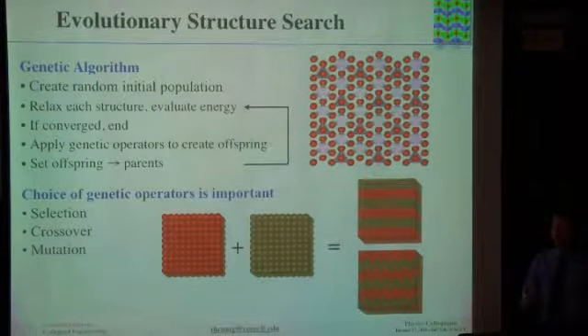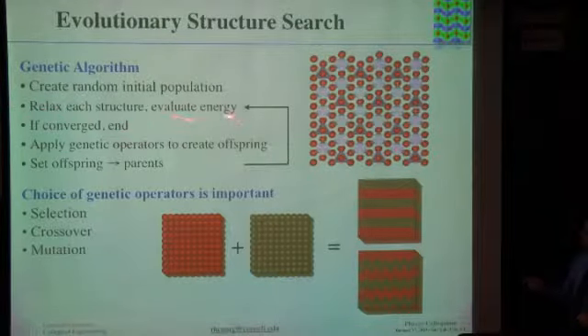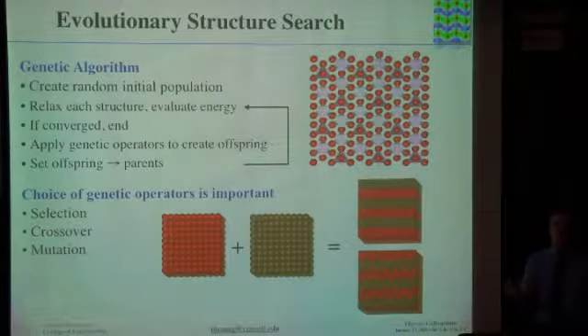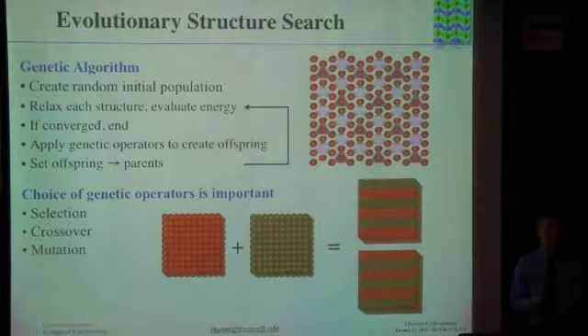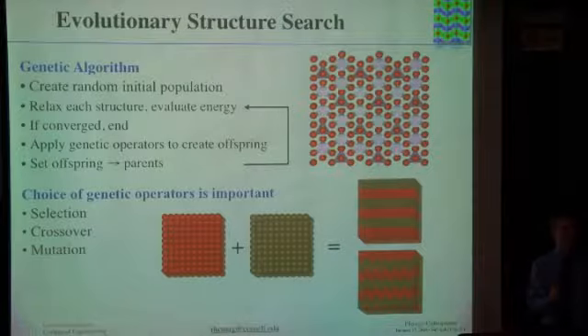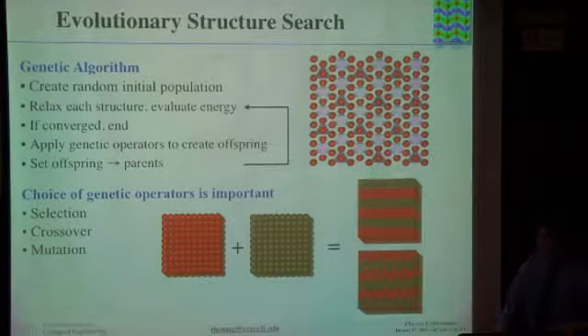We use density functional theory to now relax those structures, to take the forces and stress tensors and minimize the energy, so walk down into the nearest local minimum. That's called relaxation. We look at the energy, and you could stop there in principle. It turns out that if you do 50 to 100 random structures at a given composition, there's a good chance you might have already found a very good candidate structure. That would be the random search. In the genetic algorithm, you go one step further. You take some of the better structures from that initial random run and try to combine them in such a way that you preserve some of the structural motifs. I'm going to tell you in a second how we do that.